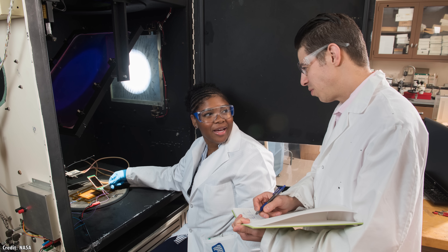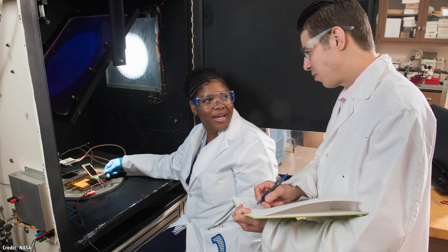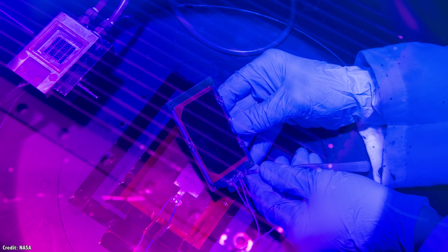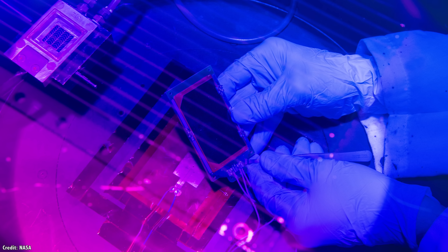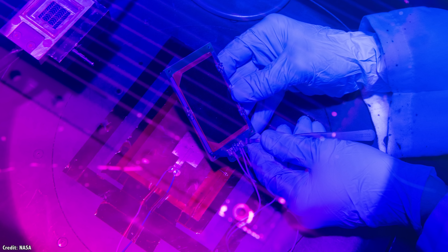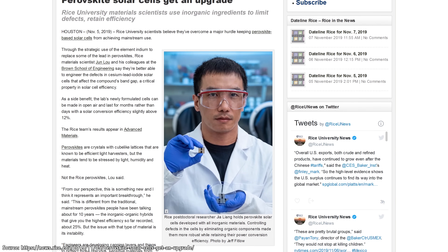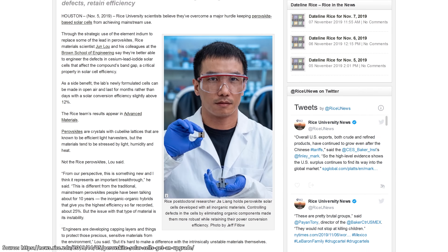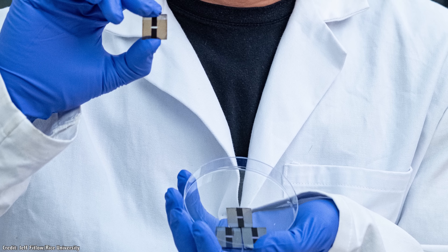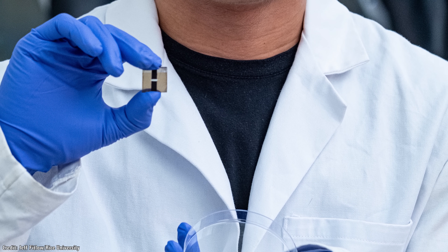There's an entirely different technology called perovskite solar panels, which might enable spray-printed panels in space. Perovskites are crystals with a cube-like lattice structure which can harvest photons. They're less efficient than photovoltaics, providing just over 10% electricity from sunlight. And unfortunately, they're also incredibly sensitive to moisture and oxygen in the Earth's atmosphere. But they have their advantages — the crystals don't need to be wired up like electronics; they can just be produced in large sheets. Researchers from Rice University announced that they've been able to overcome some of the downsides of perovskite crystals using different materials that resulted in fewer defects. They were able to make panels with an efficiency of 12% and a voltage of 1.2 volts, and the panels were able to stand up to a high humidity environment for months without degrading, while traditional crystals decayed within a few days.